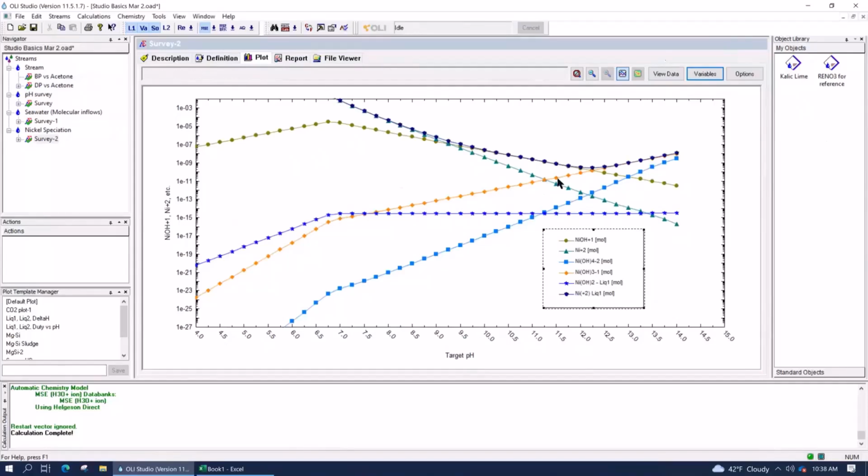So essentially, it summed up all the different species to come up with the total concentration of nickel in solution. And this is called the solubility well of nickel hydroxide. If it weren't for the solubility well, you wouldn't have a nice nickel patina or a passive film forming on your corrosion resistant alloys.